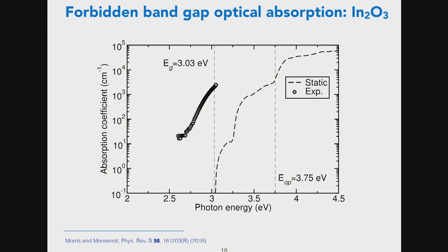So this line here is the so-called optical gap, and that's the point from which there is a strong absorption observed experimentally and also theoretically, and that corresponds to the lower lying band that has the opposite parity to the conduction band minimum. But then theoretically, we do actually get some absorption all the way to the valence